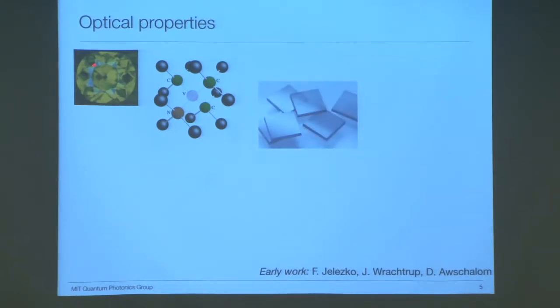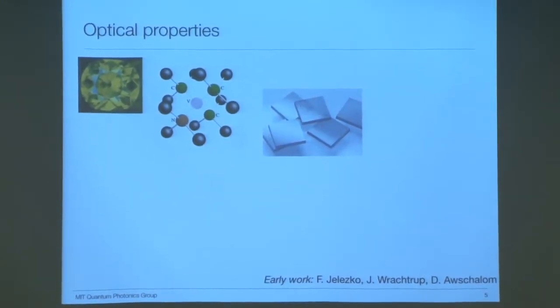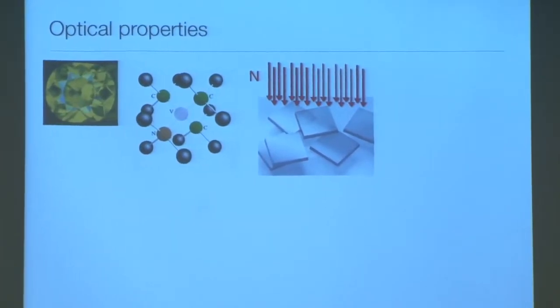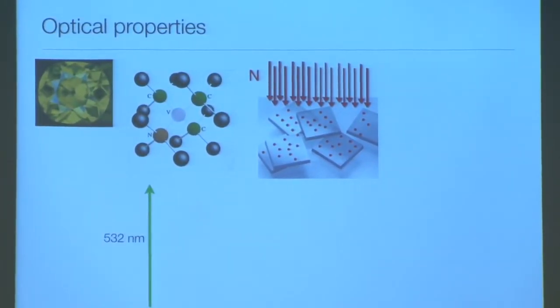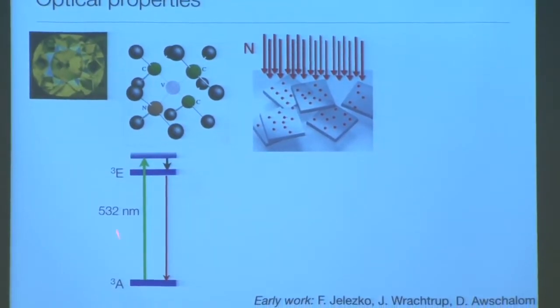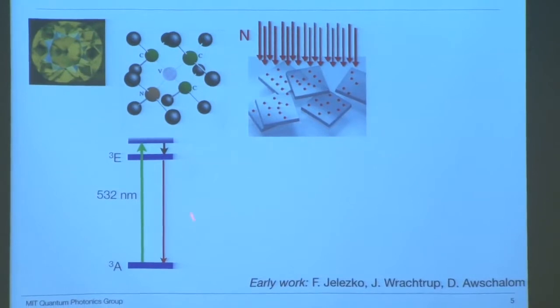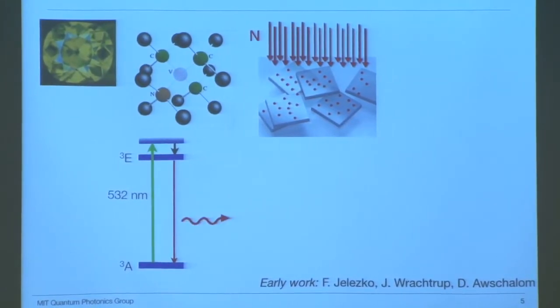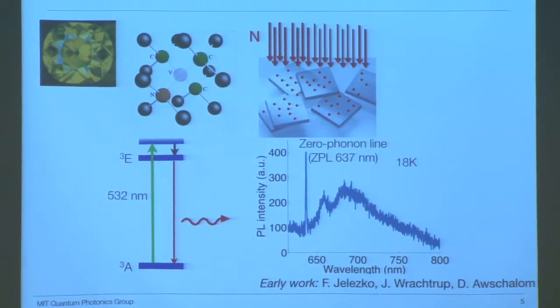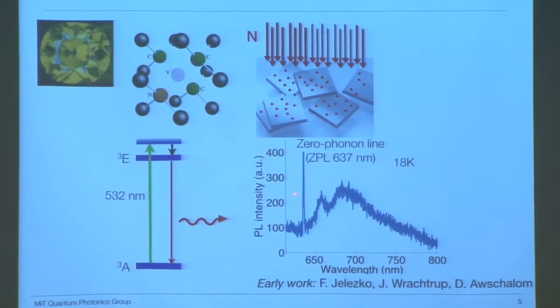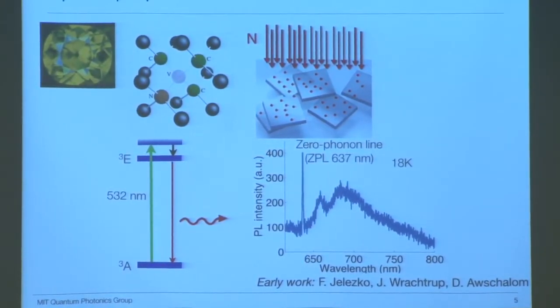Not only can NV centers exist naturally, but we are also able to produce them either via the chemical vapor deposition growth process, or by nitrogen ion implantation and annealing. Excited by the green laser, the NV electrons will be pumped from ground state to excited state and decay back to the ground state with a photon emission. In the spectrum, we can see that these NV emissions will not only be in the zero phonon line, but also via a phonon interaction through the phonon sideband.